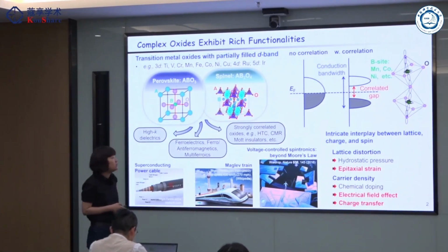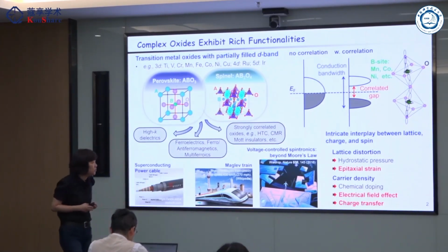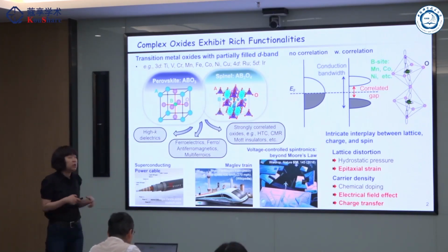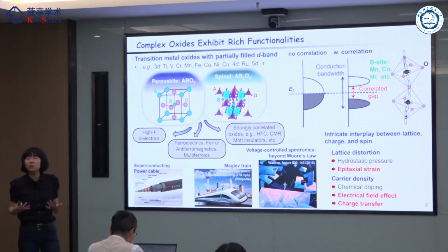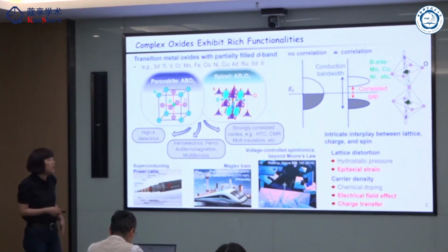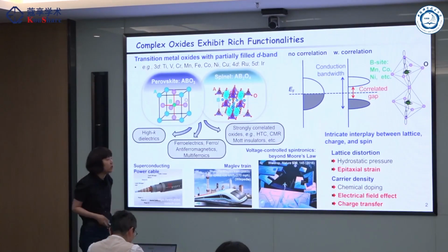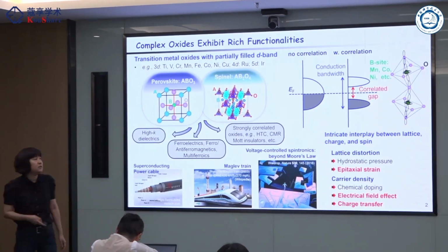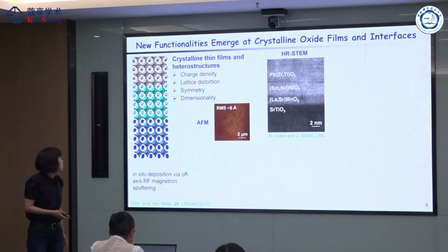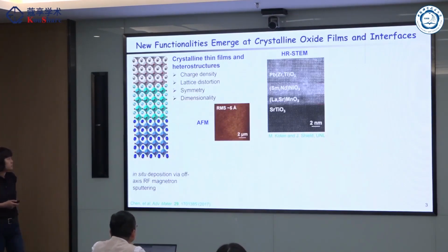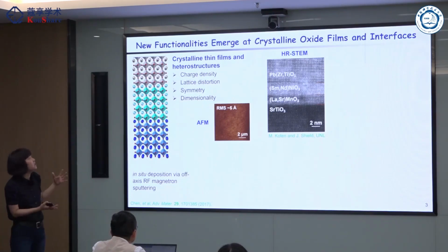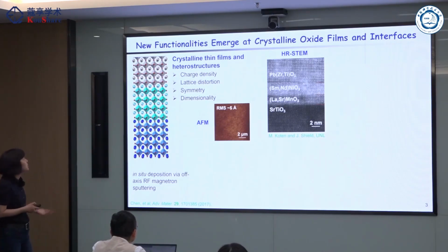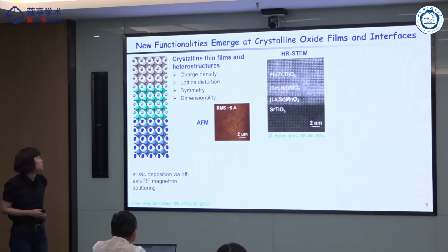There are lots of control parameters I can use to tune the lattice distortion and the charge carrier density to induce this quantum phase transition. And for thin films, you have more tools such as epitaxial strain, electric field effect, and charge transfer at the interface. So we work with those structurally similar materials, combine them into heterostructures, and use this system as a model system to control charge density, lattice distortion, crystal symmetry, and dimensionality, and see what will happen.